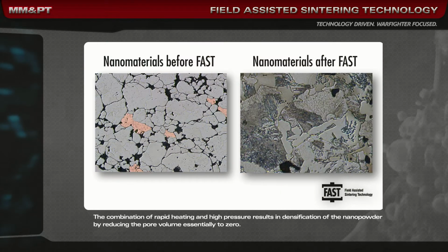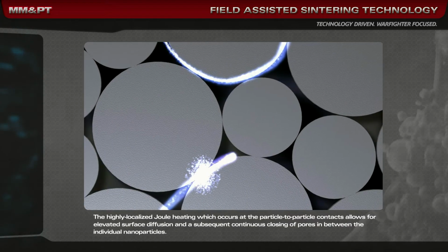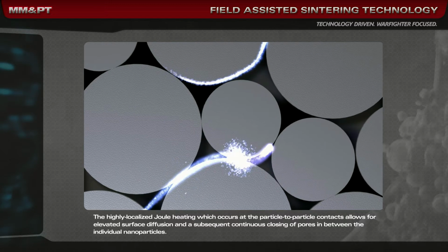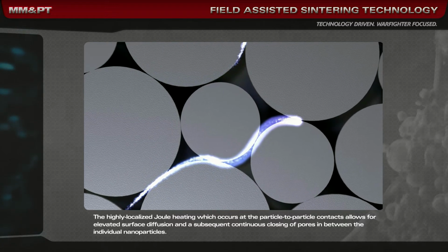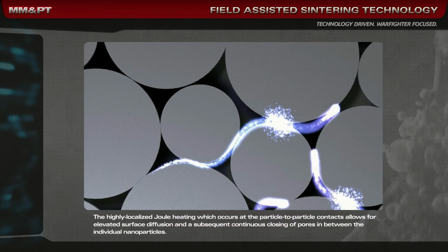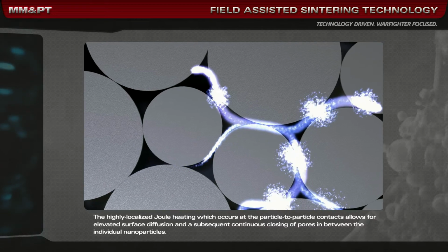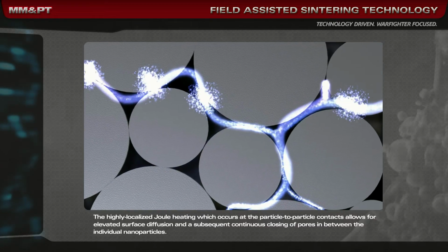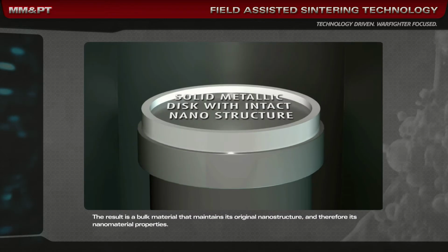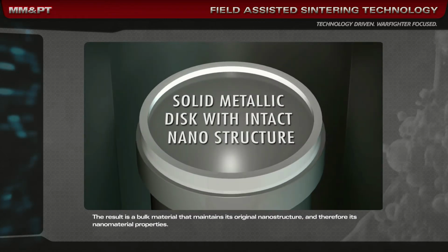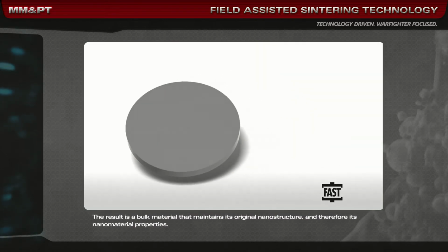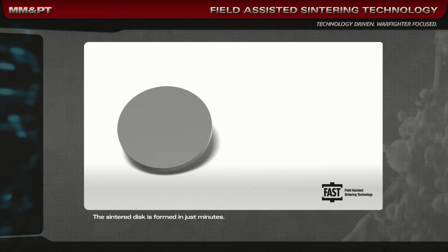The combination of rapid heating and high pressure results in densification of the nanopowder by reducing the pore volume essentially to zero. The highly localized joule heating which occurs at the particle-to-particle contacts allows for elevated surface diffusion and a subsequent continuous closing of pores in between the individual nanoparticles. The result is a bulk material that maintains its original nanostructure and therefore its nanomaterial properties. The sintered disc is formed in just minutes.